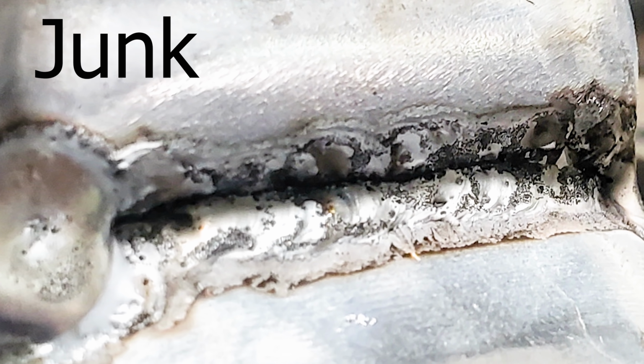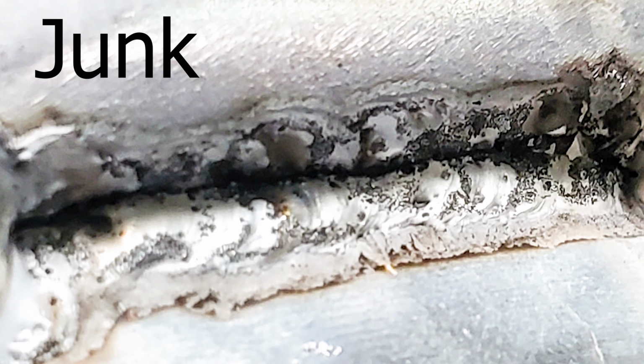The lesser quality castings usually have residual particles from the casting itself, or even from the metal that was used. Now, those particles combined with the pockets of air create a very annoying byproduct, which we often call junk. In order to make a weld stick to the part, we have to displace the junk first before replacing it with new fresh metal. The standard procedure to displace the junk is to simply run the torch over the top of the joint to create a pool. What you're effectively doing is melting it down, pushing everything out, or purging all of it out to create a nice, thick, fresh layer to weld to.